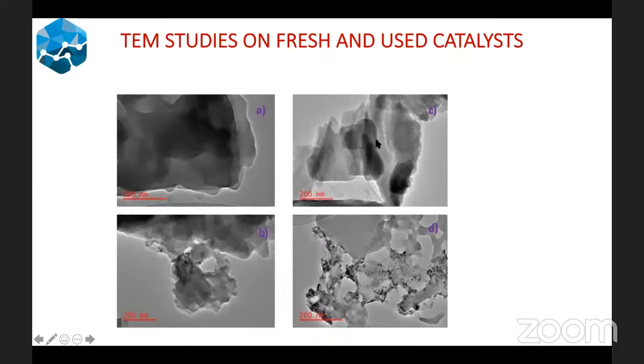C shows the TEM image of your manganese MOF before catalysis and after catalysis. And as you can see, the formation of nanoparticles here is much more significant when you compare it to image B for the magnesium MOF. So this may also explain the observed significant drop in the catalytic activity of the manganese MOF that we saw, because you can clearly see that there are some nanoparticles that have agglomerated.